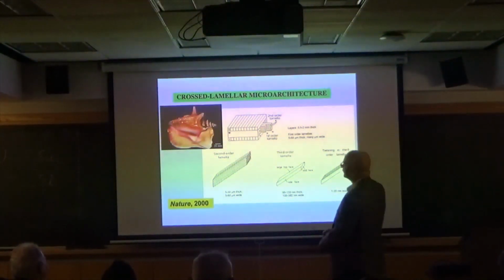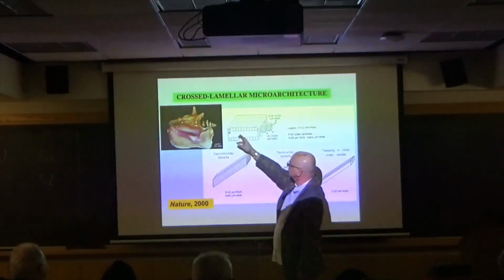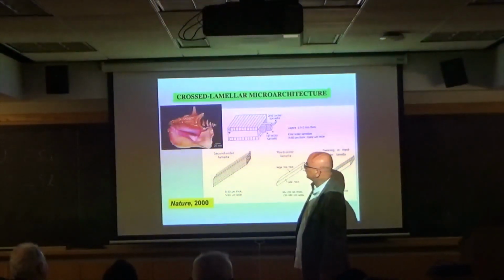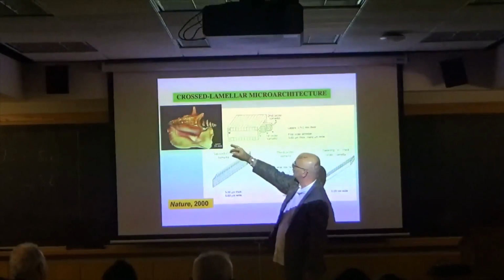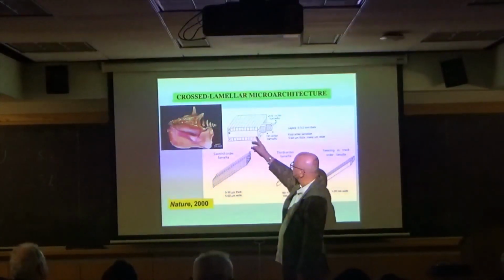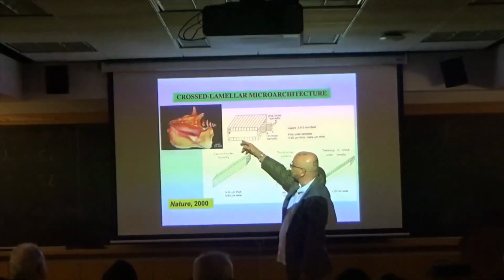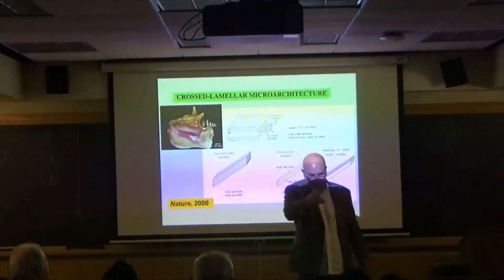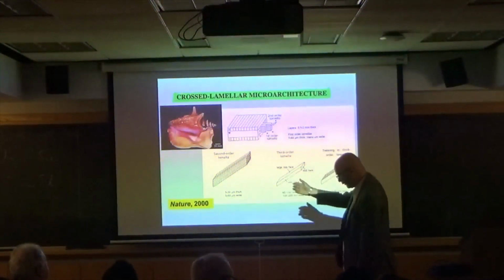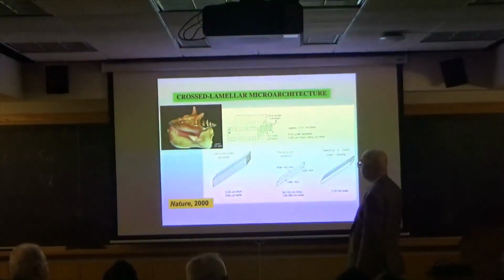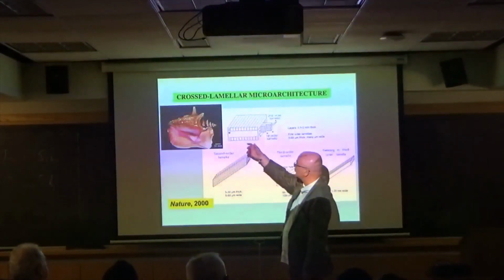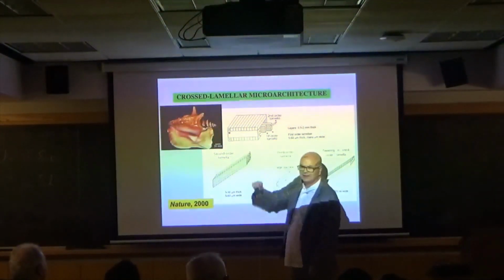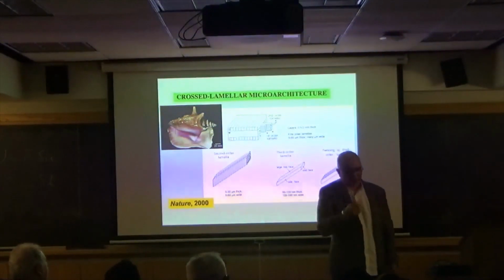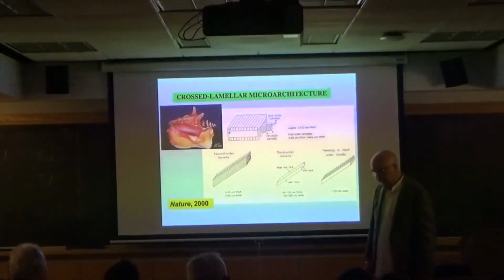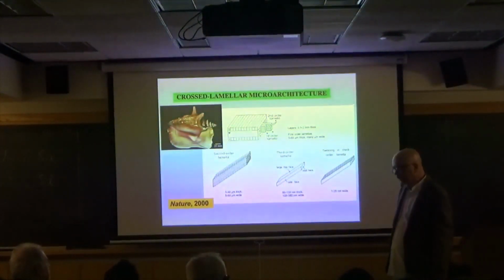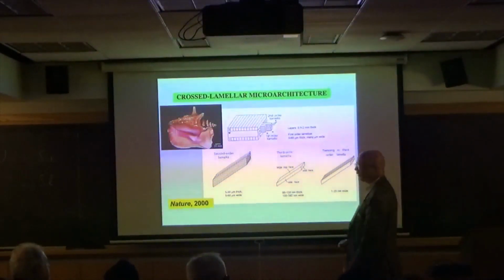But the idea is you have a problem where this is basically a nanostructure of a conch shell, which has a bunch of interfaces, and which crack. It's a very weak interface. When you bend this thing, all these cracks develop consecutively, and then they eventually saturate. And you want to find out, for example, one of the things we try to find out here is why nature designed all these weak interfaces. And it turns out that the driving force, the Eshelby force, decreases significantly as the cracks get closer and closer.